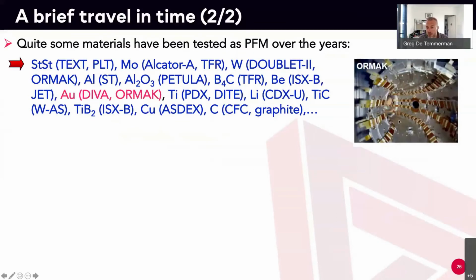Gold, my favorite. As you see in this inside view of the ORMAK tokamak in Oak Ridge in the US, you see those gold-plated plates everywhere. You might wonder whether those fusion people are rich because they put gold into their machine. The thinking at the time was that gold is pretty heavy, so it should not sputter too much, but more importantly, it should be very good for vacuum because it doesn't react with impurities, oxygen and hydrogen and so on. So it should be very good for maintaining a high vacuum and at the same time not contaminate the plasma too much. Well, it turned out it didn't work so well. It's probably a good thing, because I don't think anybody could manage to get enough gold to build a tokamak.